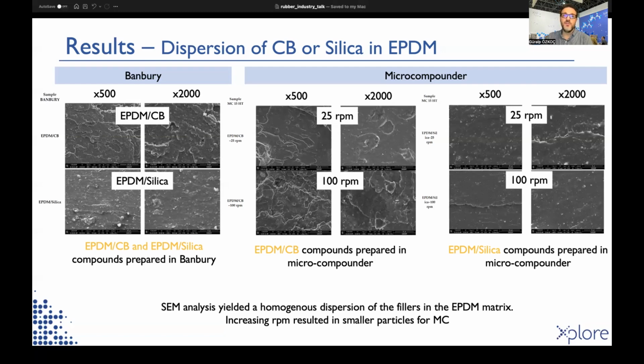The particle size of silica in EPDM ranged from 10 to 100 microns. On the other hand, the compounding of EPDM silica compounds in the microcompounder at higher RPMs led to a decrease in the diameter of silica agglomerates. The average diameter of silica was found to be 20 microns. Moreover, a significant improvement in the dispersion of silica in EPDM compounds prepared in the microcompounder at higher RPMs was obtained, as shown in the figures on the right-hand side.